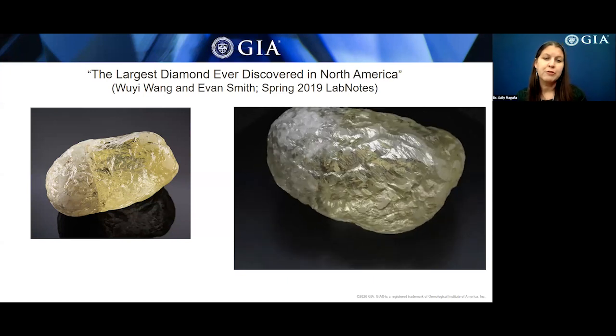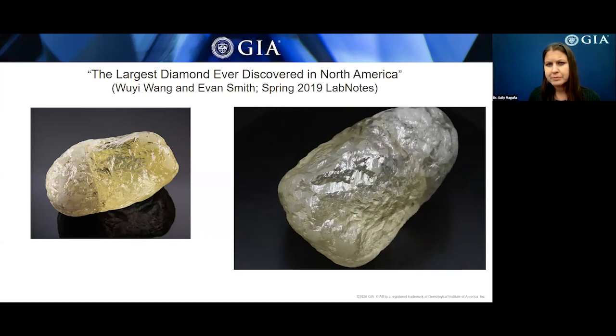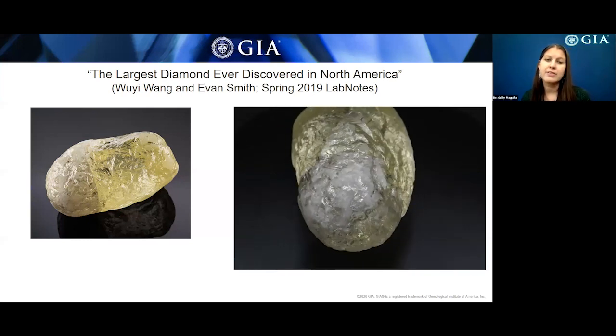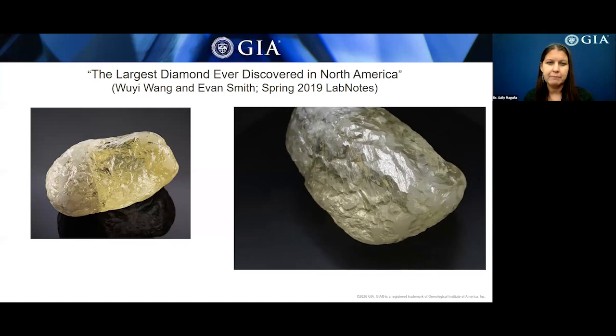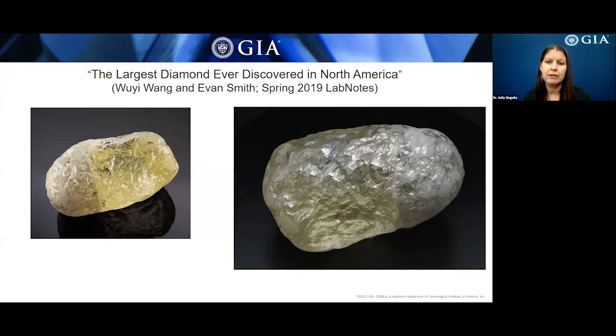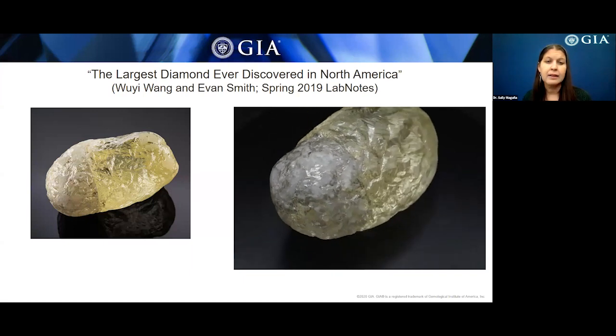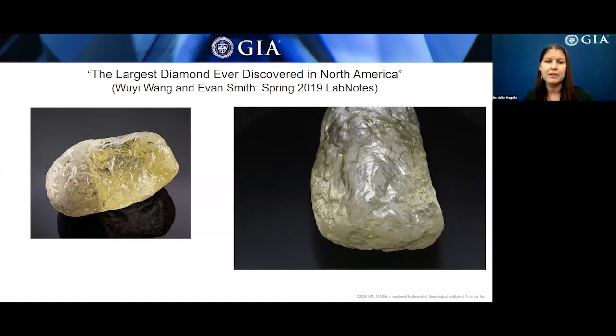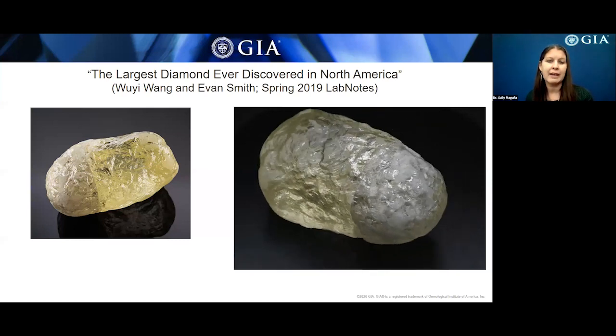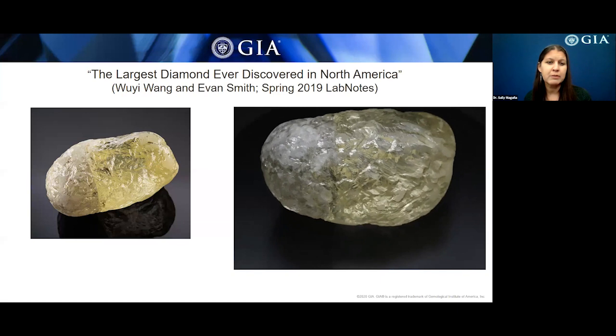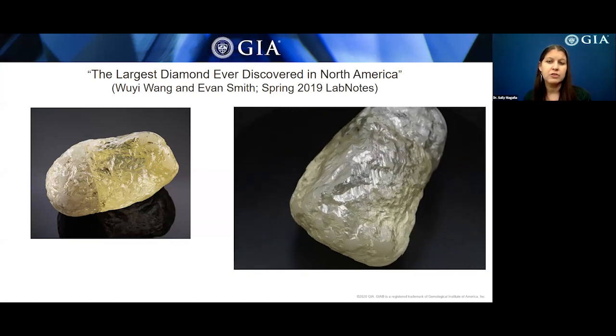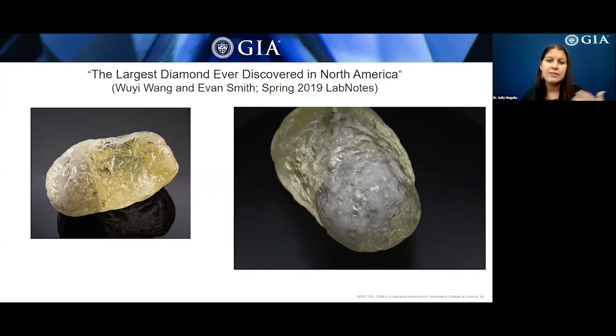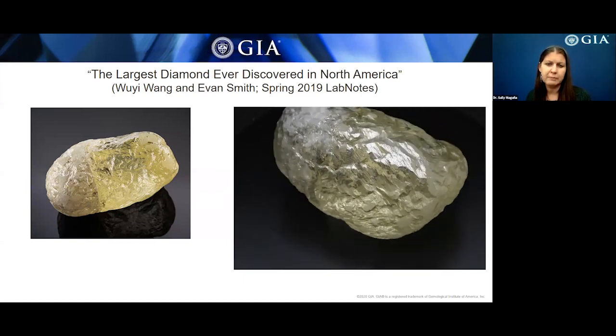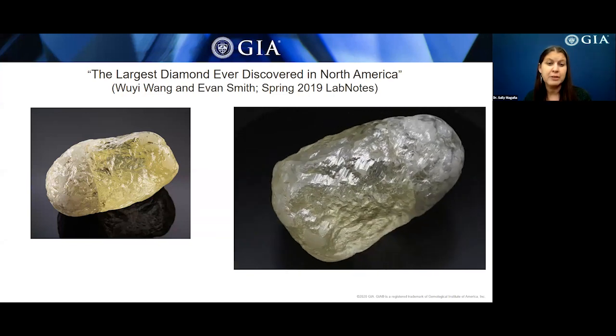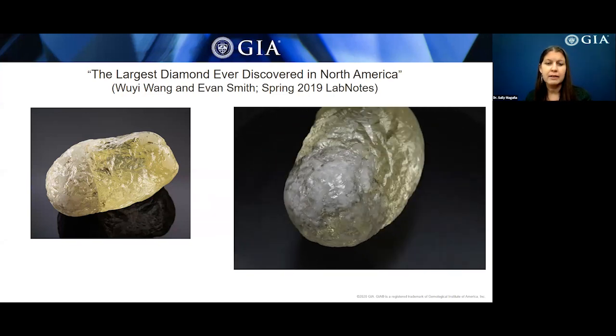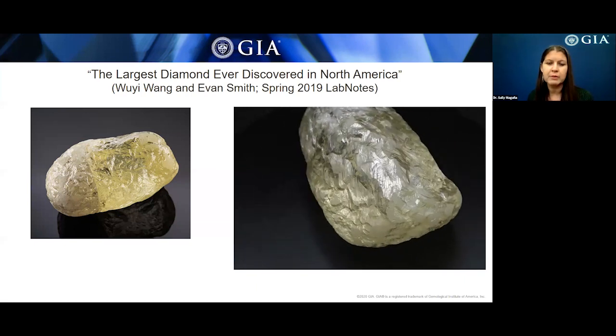This 552 carat yellow diamond from the Diavik mine in Canada is by far the largest diamond found to date in North America. The rounded shape of it is due to strong resorption of the crystal surface. And infrared absorption showed that the diamond is type 1A with a high concentration of aggregated nitrogen. UV visible absorption spectroscopy reveals strong absorption from Cape-related features, similar to that Canadian Foxfire diamond that we showed earlier. No other absorption features were detected in the UV visible spectrum, and that was consistent with the pure yellow body color that was visible to the eye.